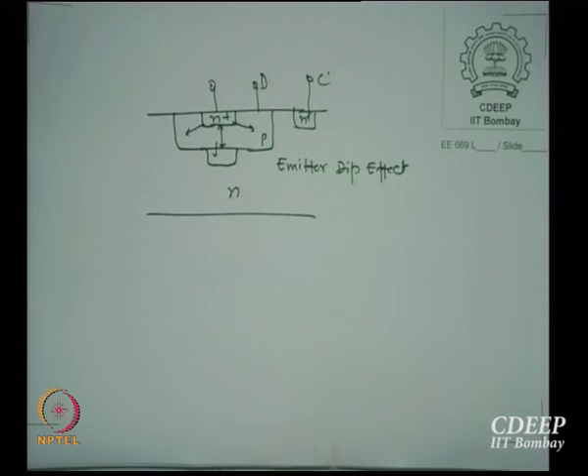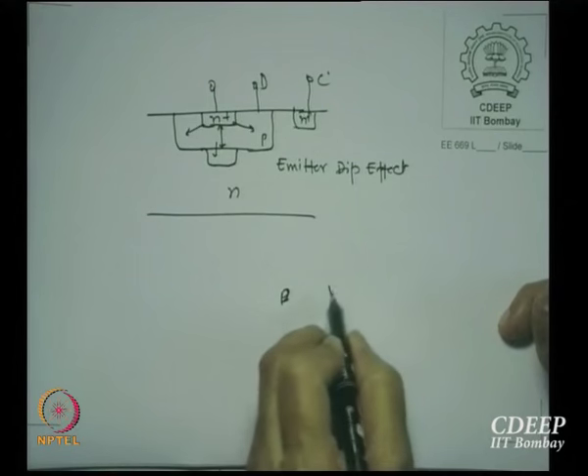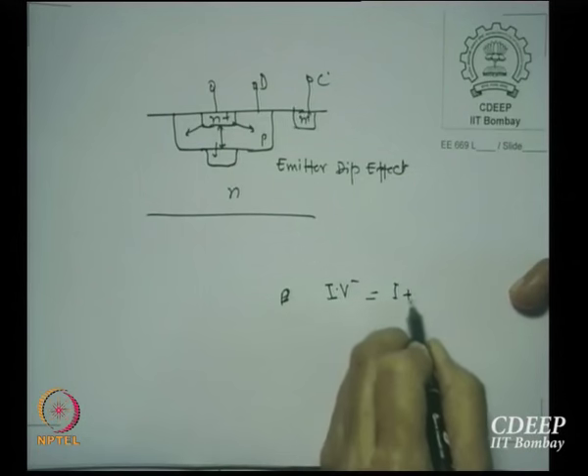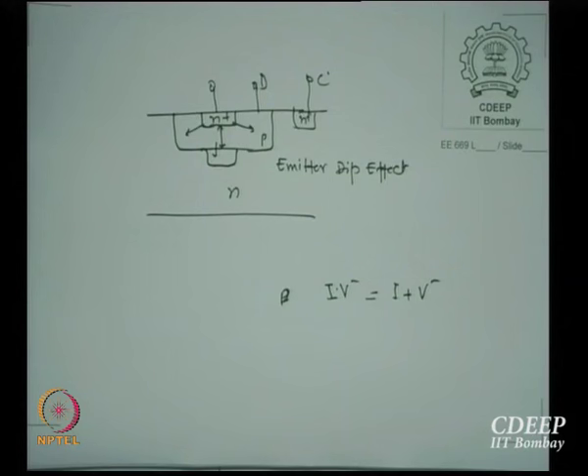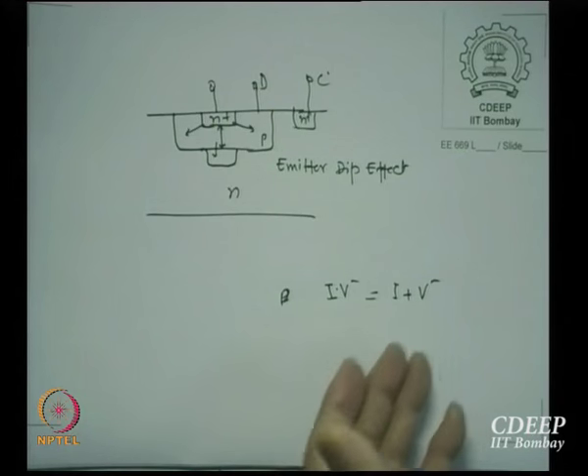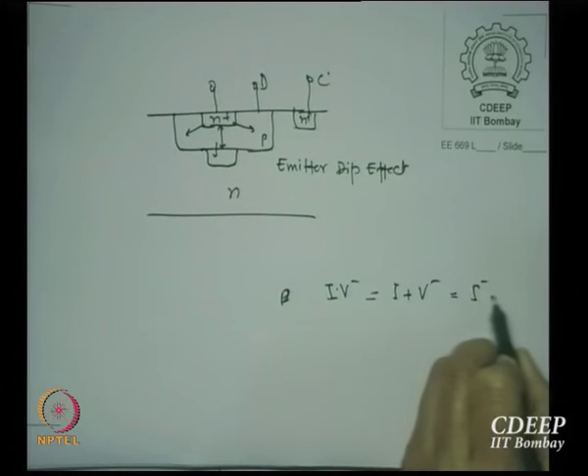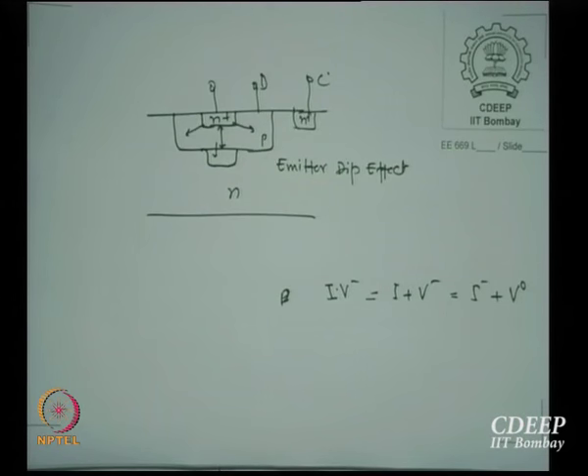They break, let us say B plus, I V minus becomes I plus V minus. So vacancies are released. As the vacancies are released, they are mostly initially minus, but it may also happen that it becomes I minus plus V0. If there are neutral vacancies created there, the boron now finds there is an additional place where it can go. And therefore, wherever these vacancies drift down, boron finds that more and more vacancies are available just below that. So more and more boron goes down through this. So the first thing is that at high concentration the pairs occur, but at lower concentration they did not. So this was one reason we said that look, this is one possibility, that the pairs might have broken down.